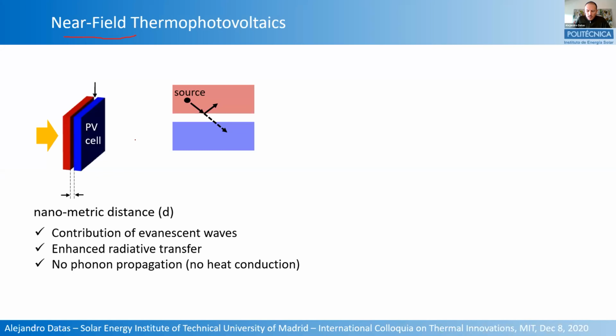The idea was established in the early 2000s, so it has been around for already 20 years. You can place a thermal emitter very close to a photovoltaic cell, so the gap between them is very, very small, a nanometric distance. In this case, if all the radiation sources are inside the emitter, typically some of these modes are totally internally reflected in this material. But if you place these two materials very, very close, then there are some photons that can tunnel this gap and then be absorbed at this site. If on this site you have a photovoltaic cell, then you can produce power out of this near field radiation.